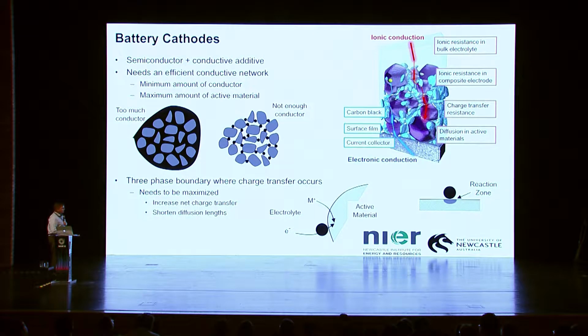What's critical out of all of it is this three-phase boundary, that interface between our electrolyte, our conductive agent, and the active material. It's at these regions around that three-phase boundary that we actually start to carry out our processes that are involved with the system.